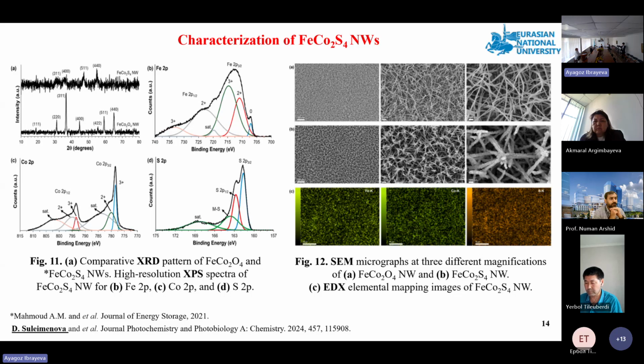Thank you for your question. For this iron cobalt S4 nanowire, we prepared it on FTO glass. This is transparent. We checked XRD on FTO and got big peaks for FTO. Then we tried to scratch off the FTO and checked XRD, but the powder we obtained was very small, not enough for a big holder for XRD. Then we used only a small amount. We checked 2-3 times, but for this iron cobalt S4 it gave a lot of noise.